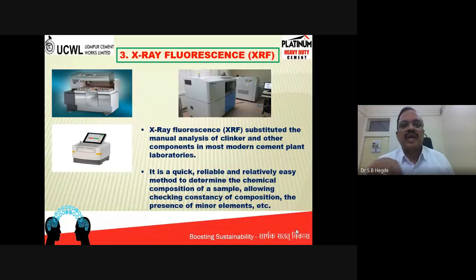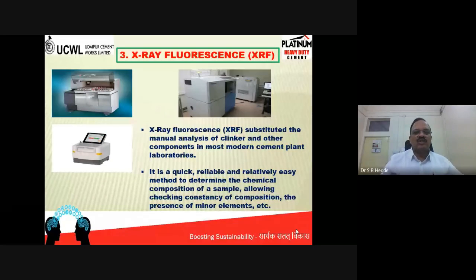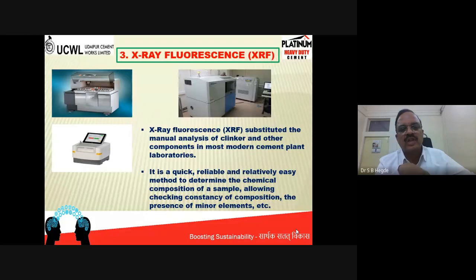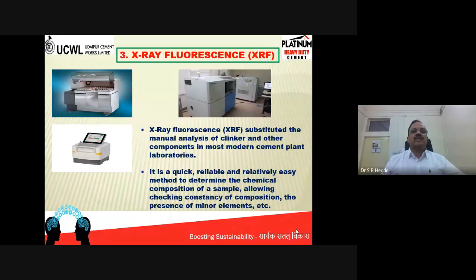And here you can see the first two on the top are bigger XRF, that is called WD XRF, and the smaller one is a small portable XRF. This portable XRF has its own limitations because it can analyze only 8 to 9 elements, whereas the bigger XRF can analyze up to 14 different oxides, even including some trace elements. Needless to say, the cost will vary accordingly. Generally, the bigger XRF will be in the integrated cement plant, and the smaller XRF is in the grinding stations.